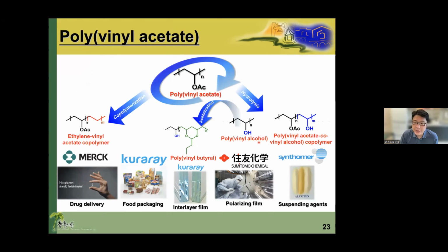These two materials are quite useful. This is a biocompatible material, and this is a hydrophilic, hydrophobic material that can be used as a surfactant. And if it copolymerizes with ethylene, you will get the EVA polymer, which is more useful. And also you can obtain polyvinyl butyral from vinyl alcohol. So polyvinyl acetate is an important plastic product on the market.